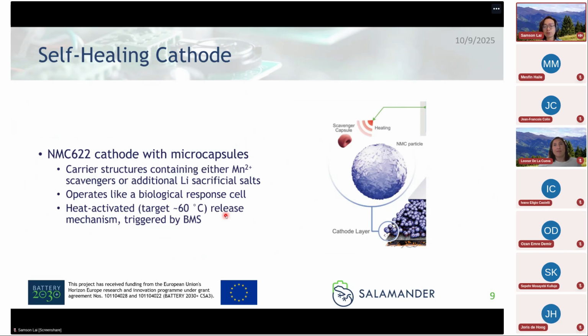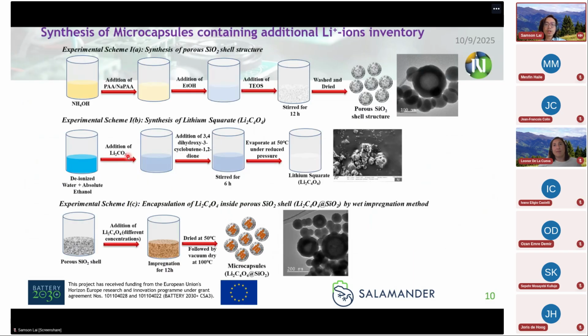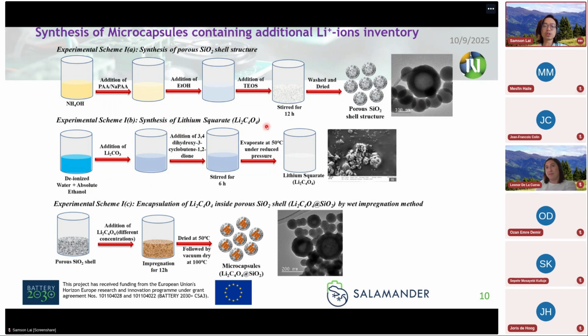We selected porous silica shells as our kind of platform, so we can create those from wet chemistry. And then we also chose this lithium squarate as our sacrificial lithium salt. This is a pretty well-known, well-studied lithium sacrificial salt. It's been used in other studies. And so we were able to encapsulate this so that now we have loaded this lithium squarate inside these porous silica shells through wet impregnation. And then we can actually just start to put these into a cell. So this is first characterization.